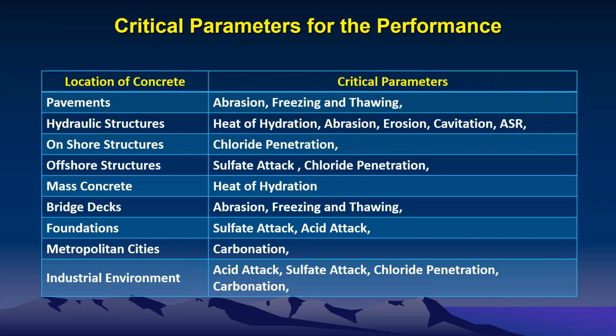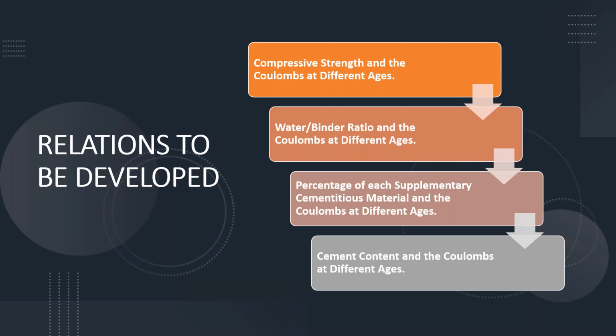If you are designing concrete for pavements: abrasion, freeze-thaw. Hydraulic structures: heat of hydration, abrasion, erosion, cavitation, ASR. Onshore structures: chloride penetration. Offshore structures: sulfate attack, chloride penetration. Mass concrete: heat of hydration. Bridge decks: abrasion, freeze-thaw. Foundations: sulfate attack, acid attack. Metropolitan cities: carbonation. Industrial environment: acid attack, sulfate attack, chloride penetration, carbonation.